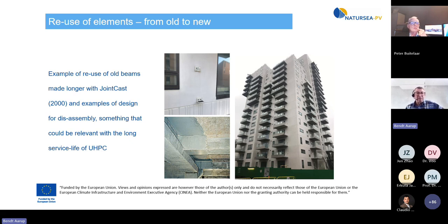The bottom left picture is from a project in 2000 where a building in Aarhus was pulled down, and they wanted to reuse some of the old beams, but with the new building system, the beams were a little too short, so we used the CRC joint cast dry mortar version of our UHPC to extend the beams a little bit so that they could fit the new system and be reused. This is something that we're looking into with the balconies and our staircases.